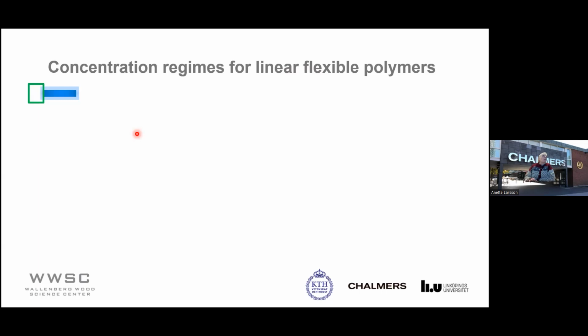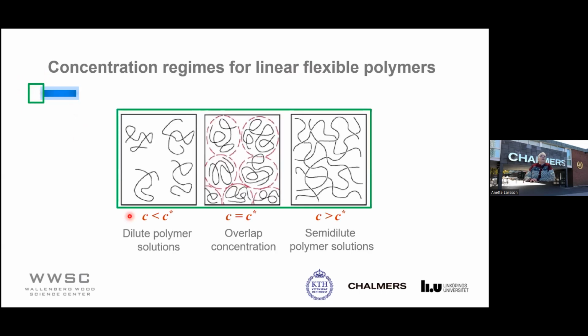And if we focus a little bit more, how does the polymer chain look like? So out in the bulk, the polymers swim around as lone polymers. So we have a dilute polymer solution. At the boundary here, between the bulk and the gel layer, we have approximately the overlap concentration. And that is when the polymer chains start to feel each other and interact a little bit with each other. And here, when they increase in concentration even more, then they start to entangle in each other. And there you have the entangled polymer solution. And the overlap concentration here is a very important parameter, and that depends on the polymer chains. So a larger molecular weight of the polymer will give a lower overlap concentration.